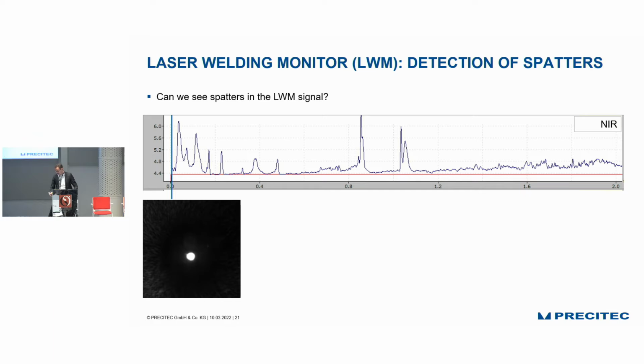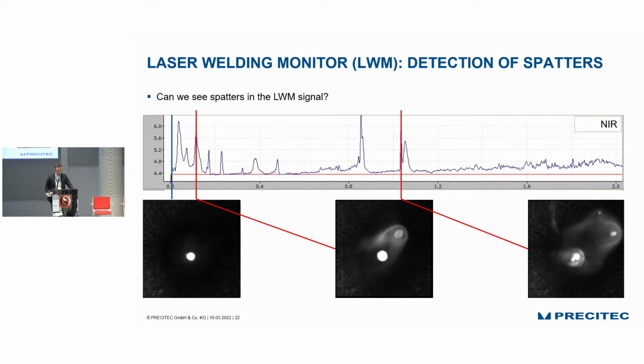Now, a second topic frequently asked by our customers is the detection of spatters. And to be honest, we performed a very bad weld in copper with infrared, really defocused, to have severe spatter events. What you will now see at the bottom is a video, a camera image, where you can see the keyhole, the white dot is the keyhole, and the signal of the photodiode which is sensitive in the near infrared. And what you can see is that each time a spatter event takes place, a peak occurs in our photodiodes. If you have a spatter event in copper, we can clearly see this in the photodiode sensitive in near infrared. If you have a spatter event in aluminum, then we can see it in the photodiode sensitive in the visible range of light.